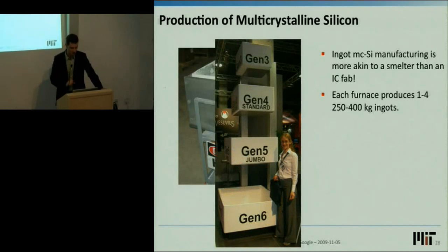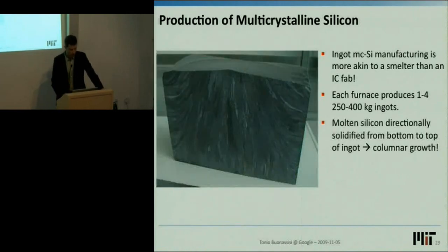The number after the gen refers to the number of wafers along the linear dimension. So Gen 5 would be 5 wafers along the linear dimension, 25 wafers total along each thin delta Z of your crucible. And out of these crucibles comes material that looks something like this. These are columnar growth structures starting from the bottom all the way to the top. And then you slice your wafers out horizontally, and your grain boundaries are running perpendicular to their surfaces and don't interfere much with charge transport.